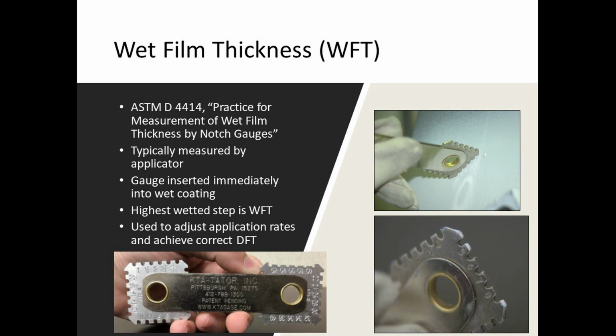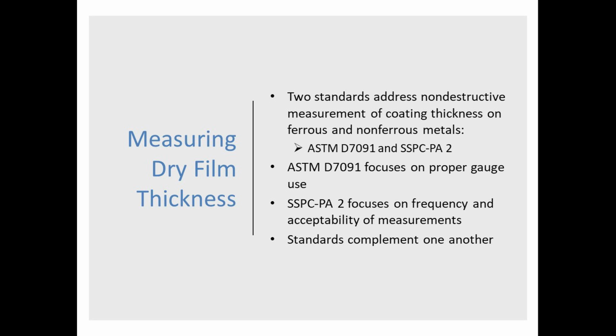Wet film thickness, something we have measured for, again, decades and decades. This isn't really a quality control checkpoint. This is more of an applicator's tool to assess whether or not they've got the correct material flow, spray pass, rate, overlaps that they need to achieve the right thickness. Ultimately, what we care about is the dry film thickness. This is a means to an end. But use wet film thickness gauges properly and don't overuse them. The aluminum ones that many folks use, aluminum's very soft. It won't last very long, and you'll find out you're going to be getting incorrect wet film thicknesses over time if you overuse them.